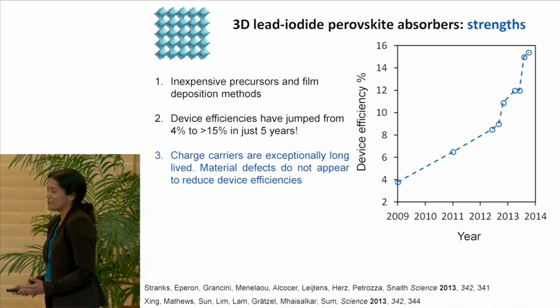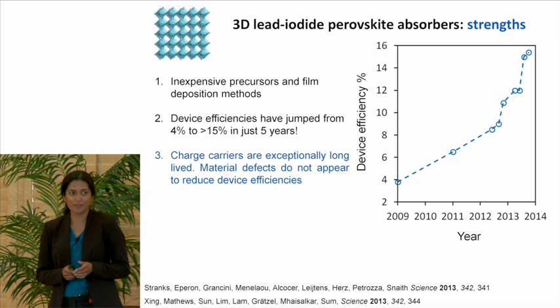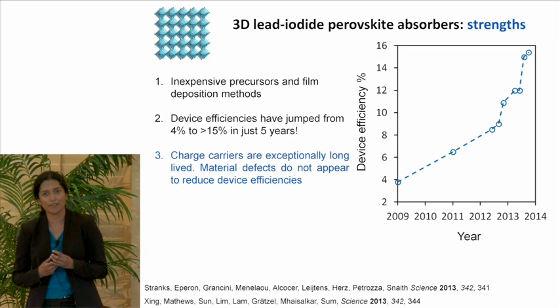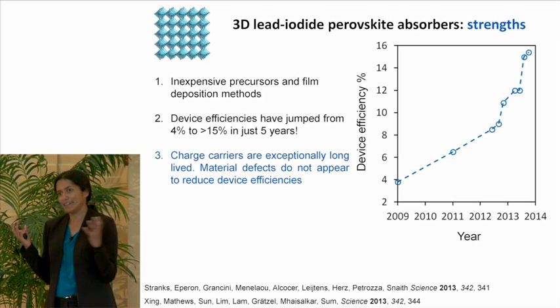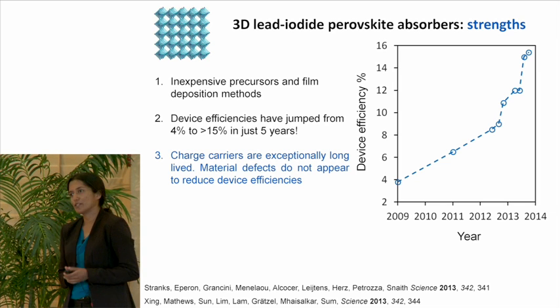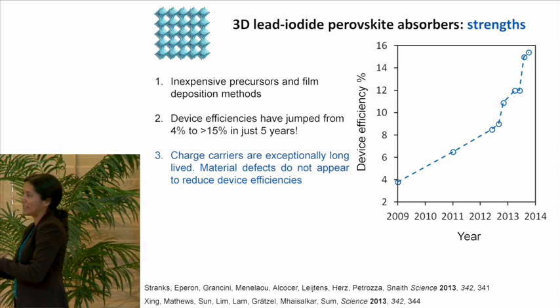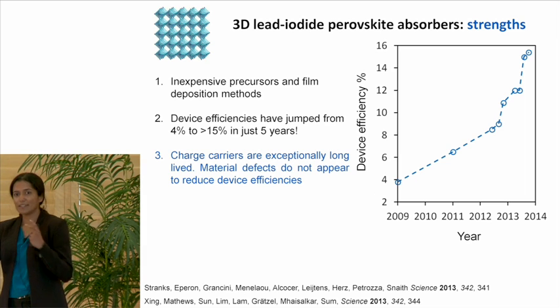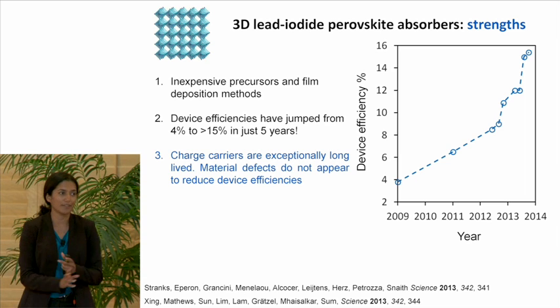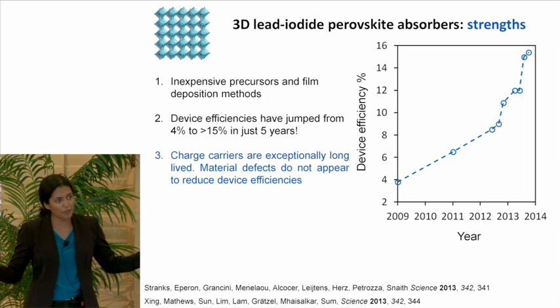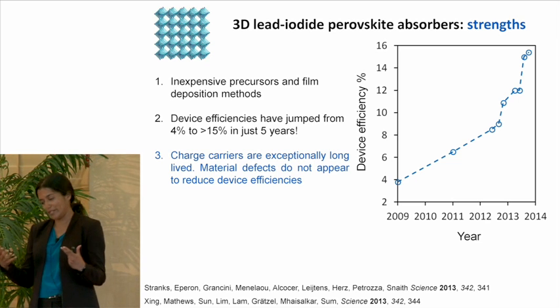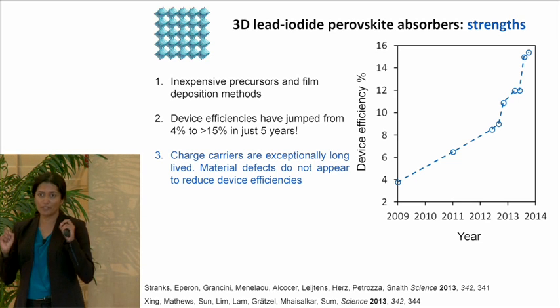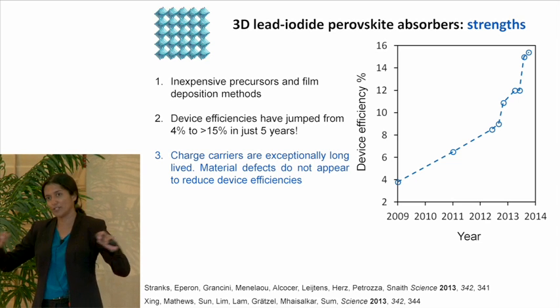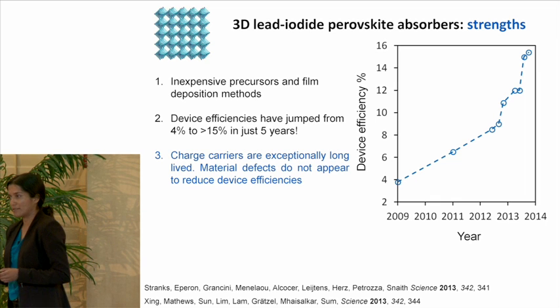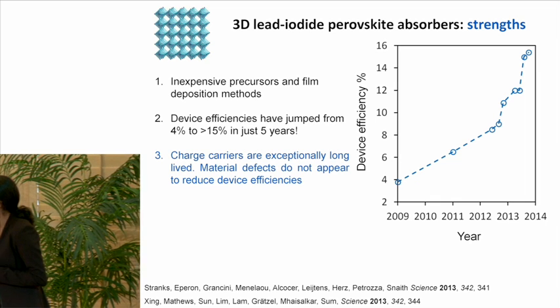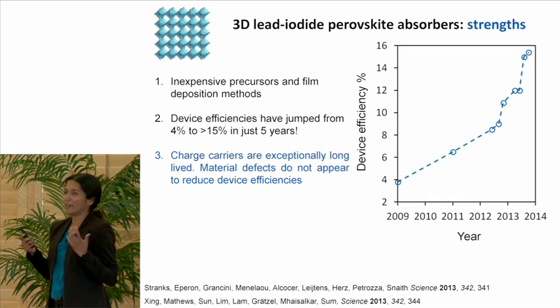So I'll tell you some of the reasons why these materials have these great efficiencies. It's very remarkable that these materials have very intrinsic properties in their photoexcited state. So when we hit these materials with light and we create photogenerated electrons and holes, these charge carriers can move around very freely. The diffusion lengths are very long, and they don't recombine very easily, which means we get ourselves some time for those holes and electrons to go their own separate ways and complete the external circuit in the solar cell device.